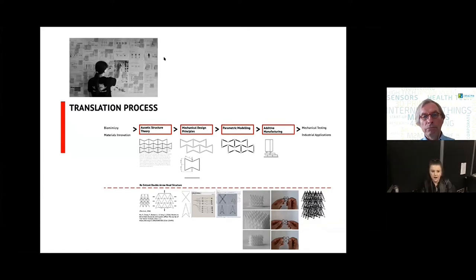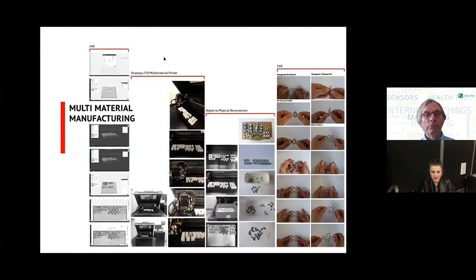So in terms of the multi-material printing we develop the structures through CAD and then at the end they are put through the GRAB CAD which is the software that the Stratasys is used to print the structures and then you can see the J750 that's the main printer there. The structures come out with a huge amount of support material on them. We try to reduce this through material and design optimization but essentially the support material can come in two forms: water removable or soluble through a chemical bath and so some of the structures are put through a chemical bath but obviously that then interferes with some of the elasticity properties and so we're careful with what goes through the chemical bath and what is manually removed. All the structures on the right are manual removal and then they all are exhibiting the auxetic effect through the hinge design and the strut design as well.